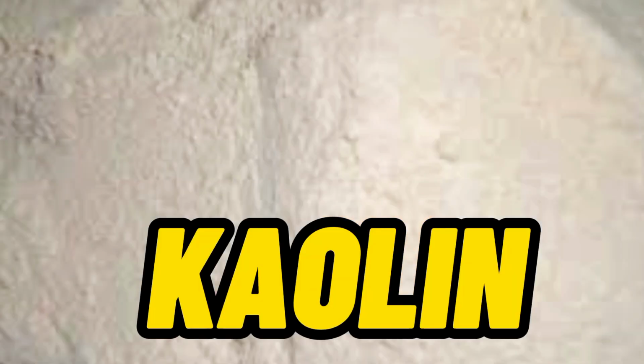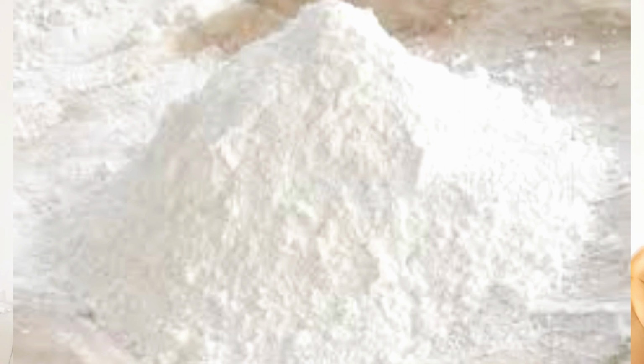So, number three is your kaolin. Kaolin is another type of extender used in paint manufacturing. They are also used to increase paint body thickness and increase plasticity. They are optional when producing emulsion acrylic paint, but a must when producing textured paint. However, it should be avoided when producing white paint because kaolin is mainly off-white in color, and as such, will reduce the intensity of the white paint. But if you can lay your hands on white kaolin, you can use it as well.